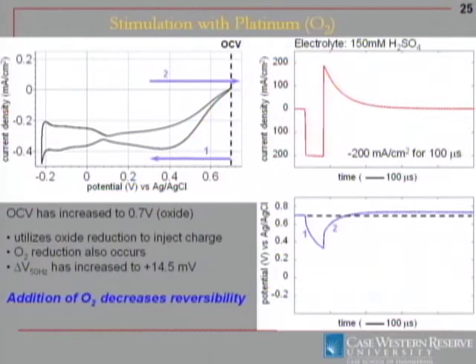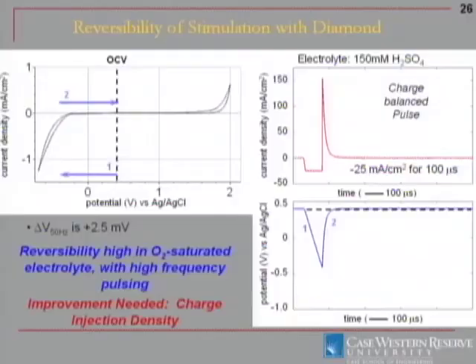So adding oxygen definitely on this time scale, just like what we saw with the Voltammogram with the charge storage capacity measurement, the oxygen decreased reversibility. With diamond, I won't show you both nitrogen and oxygen. I will just show you the oxygen case because it didn't really change much. Very little irreversibility in terms of the voltage being above the open circuit potential where we started. So we do believe that diamond could possibly be more reversible than platinum. At least this is what this is preliminarily showing.